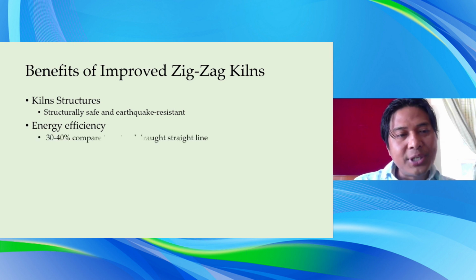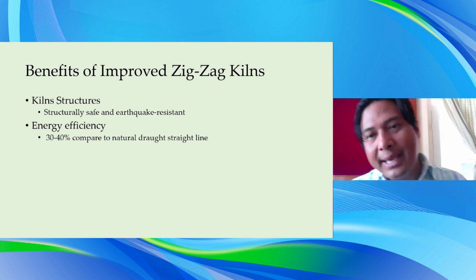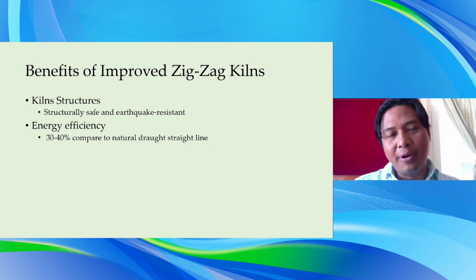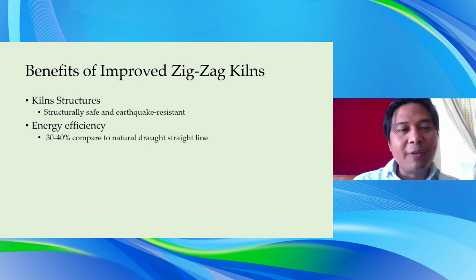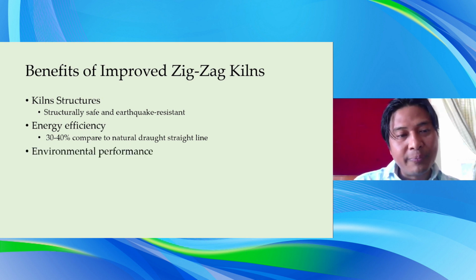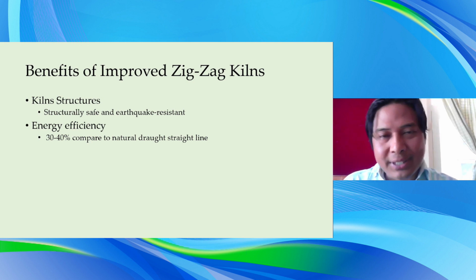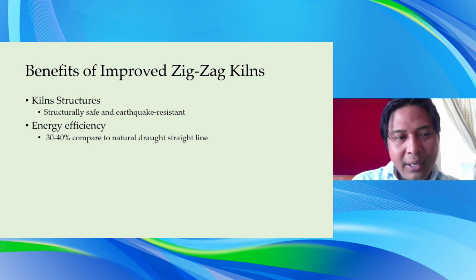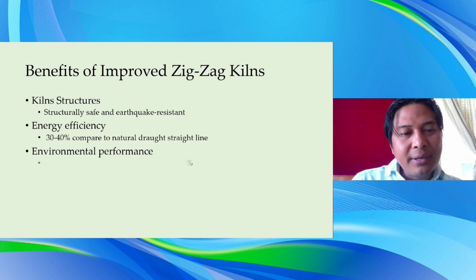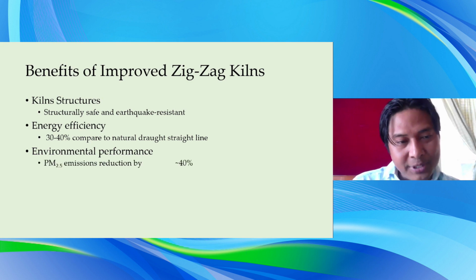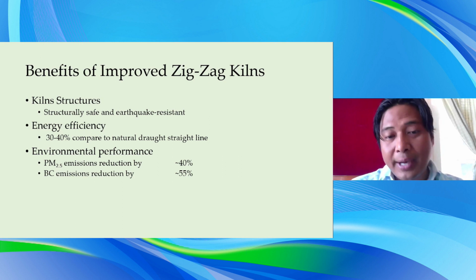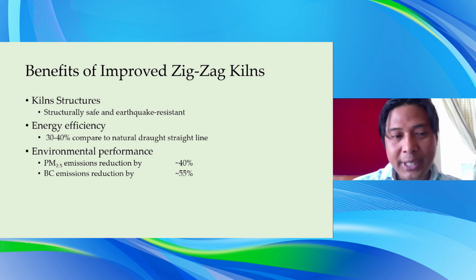And another is energy efficiency. Since we are able to control lots of air leakage from this improved kiln, the efficiency of the kiln is quite high. We can experience that about 30 to 40% of fuel is saved because of this improved zigzag kiln. And another salient benefit is environmental performance. The environmental performance is quite good in the new improved design, which has about PM 2.5 emission reduction.